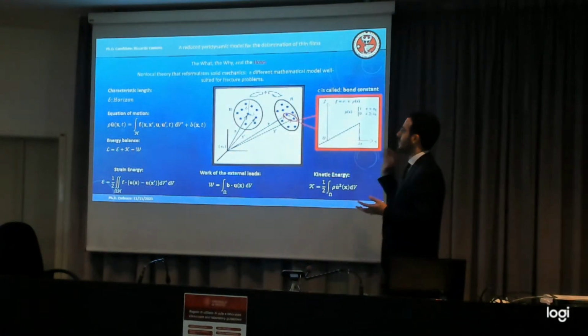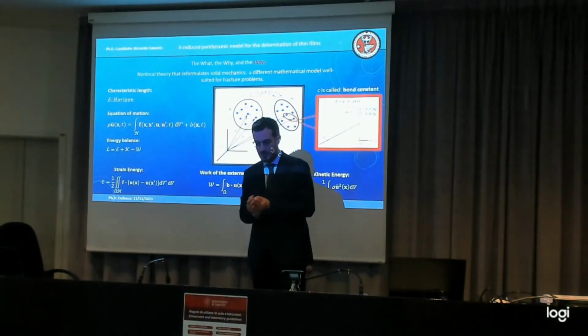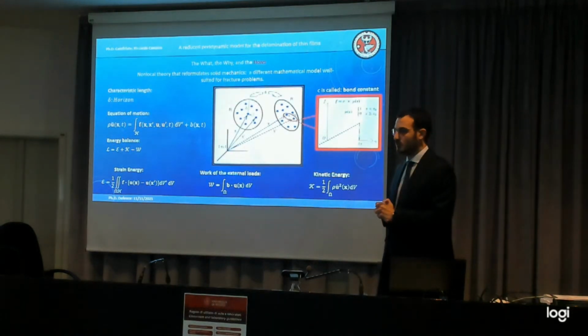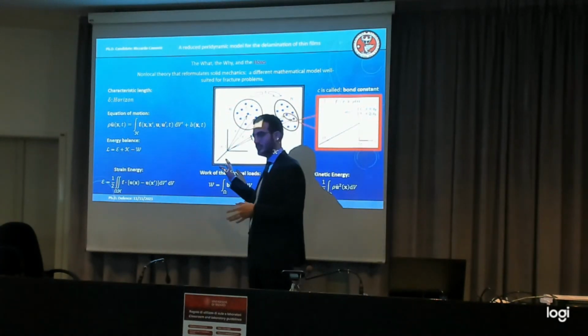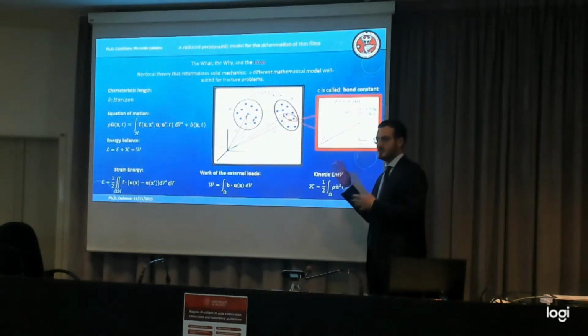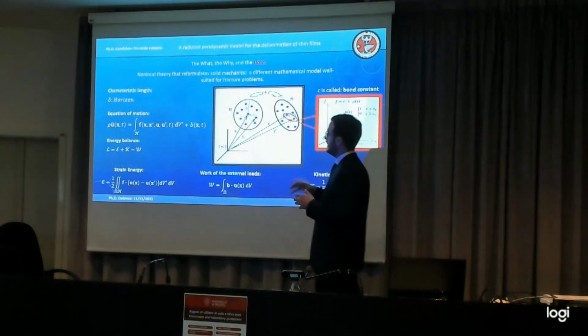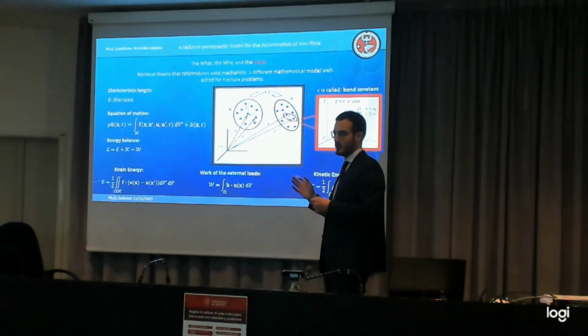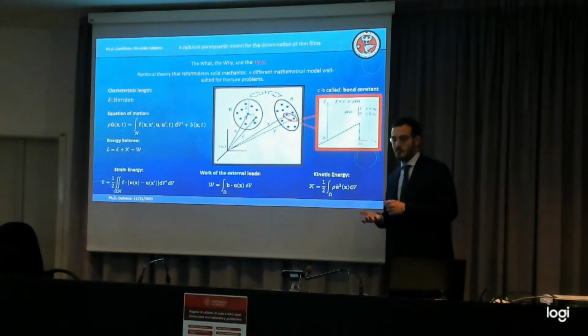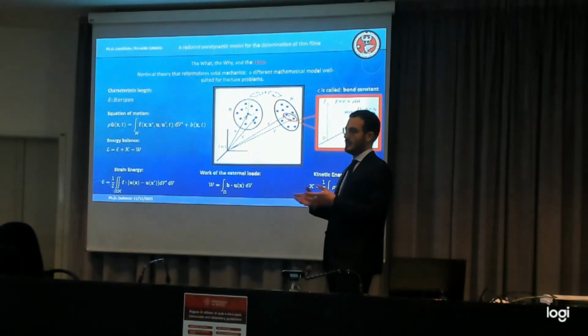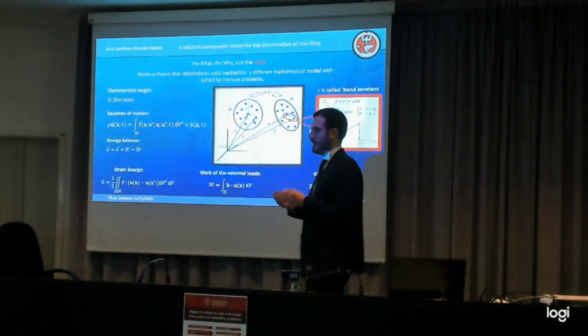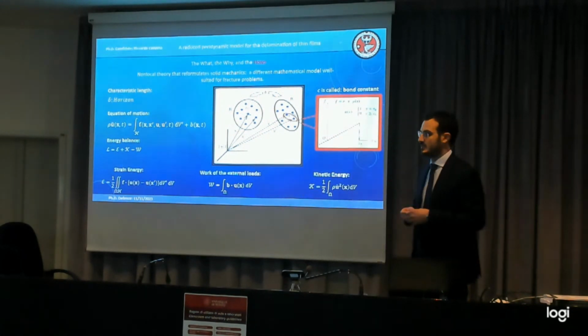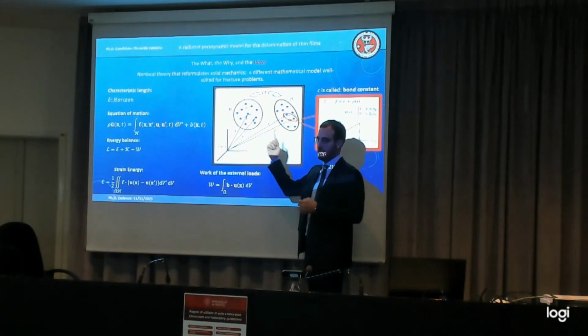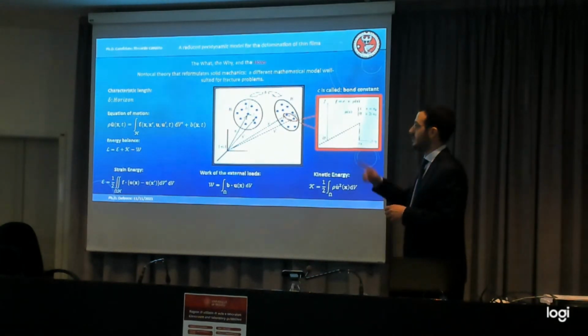So what did we do in order to produce this reduced formulation? Well, we decided to implement the peridynamic model. The peridynamic theory of continuum mechanics is one of the possible non-local theories available. It has a feature that makes it particularly well suited for fracture problems. The theory, from the physical point of view, imagines the body as a collection of particles that can interact with one another depending on the relative distance. There is a maximum distance at which two particles can interact. That is called the horizon, and it's the characteristic length for the internal length of the microstructure.